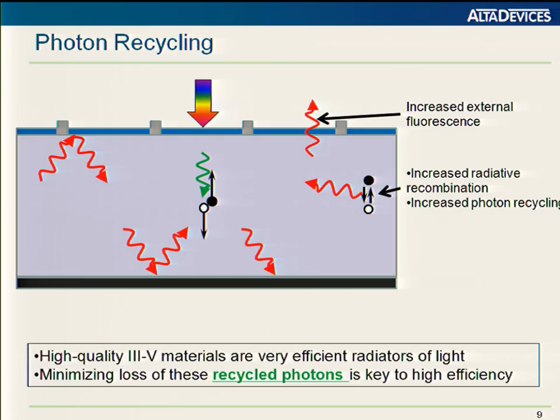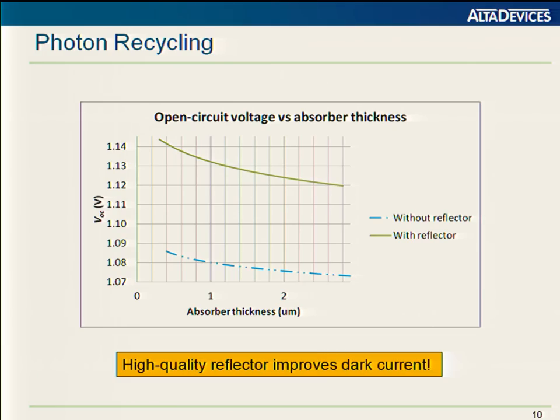One byproduct of that is that at open circuit, you have 10 times as many chances of the band edge emission escaping from the cell. So you have increased external fluorescence. High-quality III-V materials are extremely efficient radiators of light, and if you design them as an optical device, you can get extremely efficient outcoupling of the band edge emission. This increase in the carrier density and the external fluorescence of the cell is seen in the modeling as a huge boost in the VOC. Remember, we were talking about VOCs below 1.05 in practice, where we've demonstrated 1.12. So that's, I guess, an 80 millivolt boost on previous records.